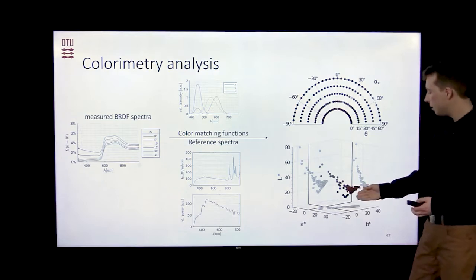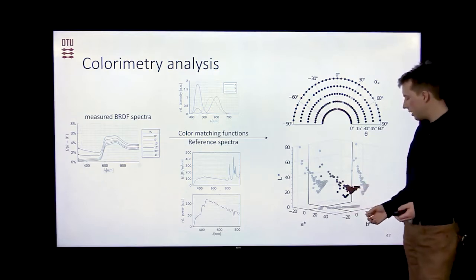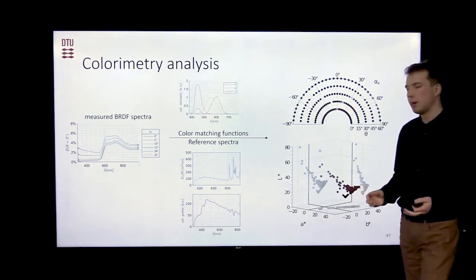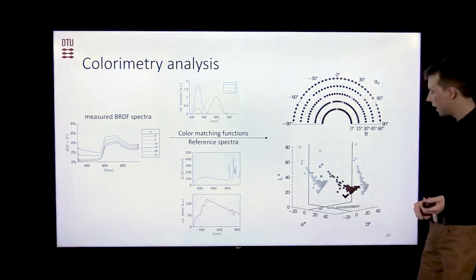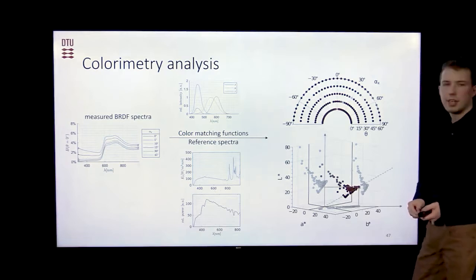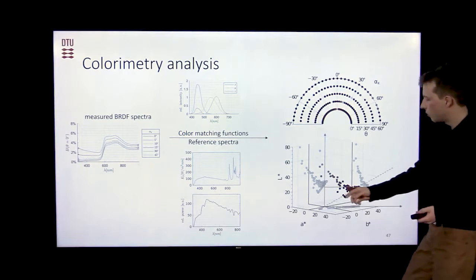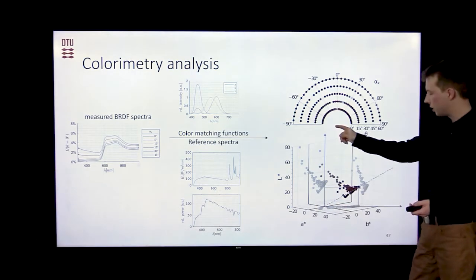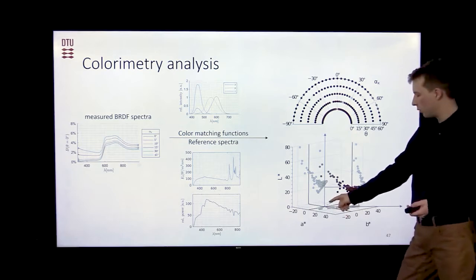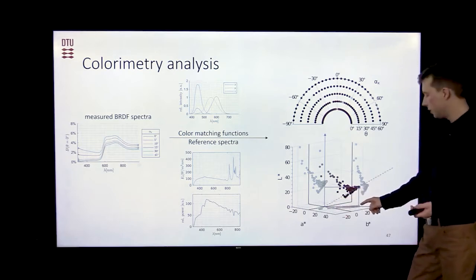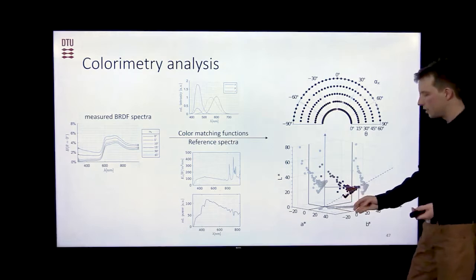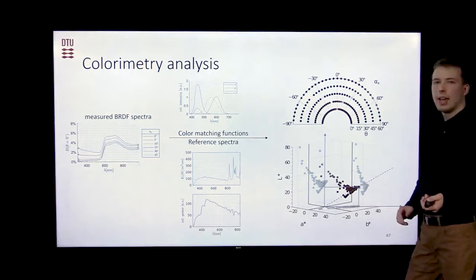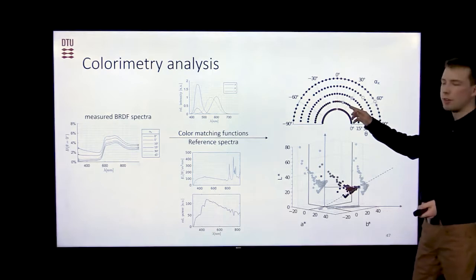And if we look at the LAB graph, here the main figure of merit is the closer our points are clustered together, the more uniform the sample appears from all angles. Additionally, we can see all the parameters I described before in this graph. The vertical axis is the lightness, giving us the degree from black to white of our color. The distance from this vertical axis is the chroma, or colorfulness, and the orientation in this graph on the AB plane gives us the hue of our color. I also mentioned these white points in the graph up here.